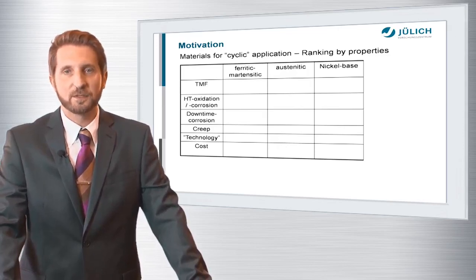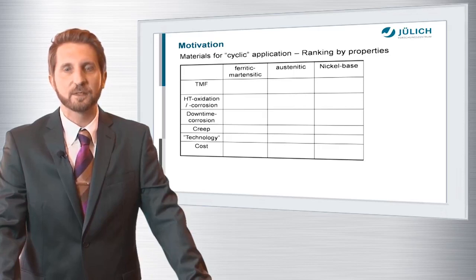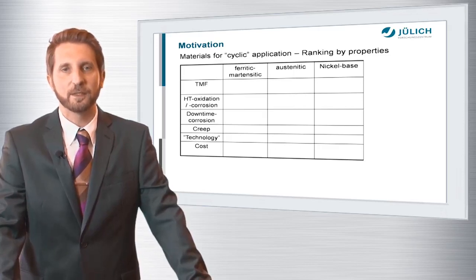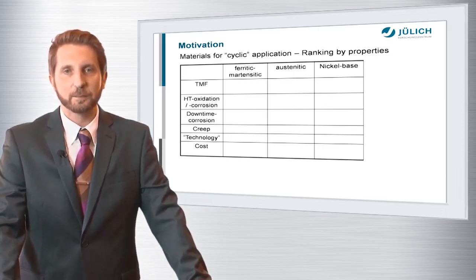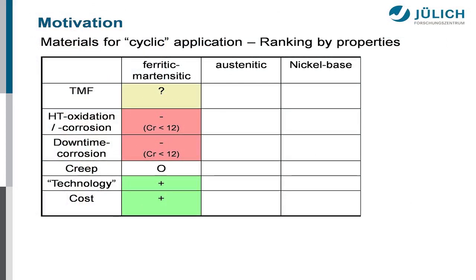Furthermore, we do have austenitic steels and high-performance nickel-based alloys. And in the motivation part, in the very beginning, I've been talking about cyclic power plant operation. And if we now rank these material classes by material properties which are crucial to cyclic operation, you first have to mention TMF, which means thermomechanical fatigue resistance. And to be very honest, even if the ferritic martensitic steels are, let's say, the most important material class today, there is not a lot known about thermomechanical fatigue resistance of these materials.